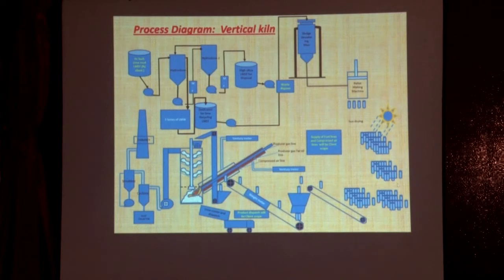So these are the pellets. Pellets are dried in the open sun area for 30 days. It automatically achieves dryness as high as 85% to 90%. Now these pellets are fed into the vertical lime kiln. They come from baffle to baffle and finally are controlled here in the heat. There is a disc below, which continuously rotates at 1 to 5 RPM, and by flame we are burning these pellets. By providing a gate, we can take out the lime. This lime can be transported anywhere, crushed and reused.